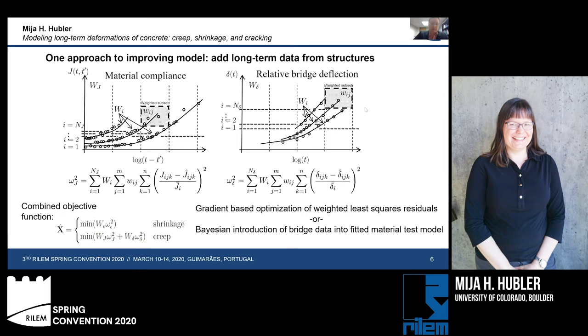Now, one approach to improving this modeling process is to add more data. So a few years back, as part of my PhD thesis, we added the long-term data from structures to our data set. The way we did this is on the left side here, you see the material compliance is captured in the logarithmic timescale. That material compliance data will provide information about how the material deforms only at the short term, because these are from laboratory tests. Okay, and then from bridge deflections, we can get the long-term response of the data. And so here we have the deflection of a bridge, which can relate to the long-term behavior of the material.